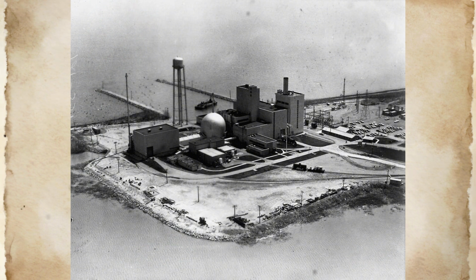The physical mechanisms that destroyed fuel within the Fermi 1 reactor core unfolded through a precise sequence of thermal and metallurgical processes that followed predictable physics principles while remaining undetectable through the reactor's available instrumentation until the damage had become irreversible. The fuel destruction resulted from the interaction between reduced coolant flow caused by debris blockage and the continued generation of fission product decay heat within metallic uranium fuel that was not designed to withstand the thermal conditions created by severe flow